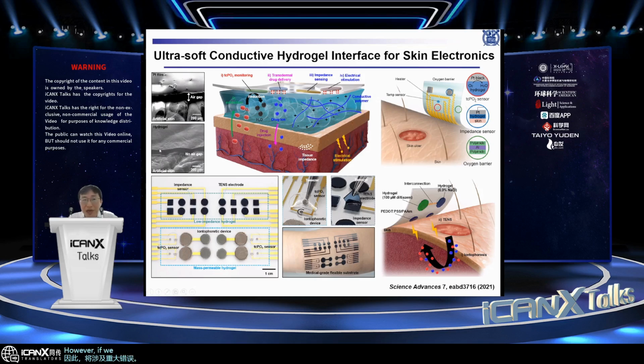However, if we use a hydrogel layer, an ultra-thin hydrogel layer, first of all, hydrogel can make a very good conformal contact to this rough skin surface. Also, hydrogel contains water, and that water can exclude external air. Therefore, the oxygen extracted from the blood vessel can be transported through the watery, moisturized medium, hydrogel, and then those oxygen molecules can be analyzed electrochemically by the TCPO2 sensor. So in that case, the signal quality and the error amount can be significantly improved.